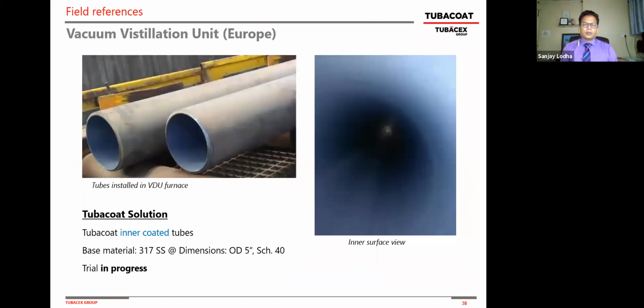Another vacuum unit furnace in Europe has been running close to 2 years now without having to decoke. We don't have any data other than it has not been out of service. It has not gone into decoking. Again, 317 stainless steel, OD is 5 inches, schedule 40, and you can see the tube surface. Trial is in progress now. It's close to 2 years. Next slide, please.